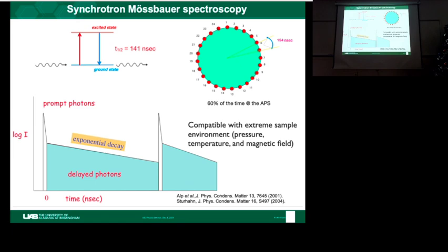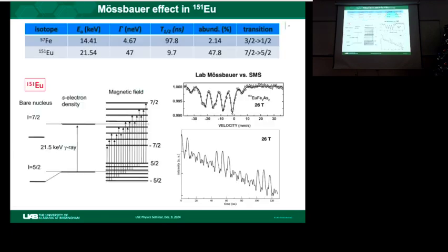And because the synchrotron beam can be focused to a very, very small size, typically several microns, or even now after the upgrade a sub-micron size, and synchrotron light has much higher brilliance than a typical lab X-ray source, you can easily integrate it with a pressure or temperature or magnetic field environment and enable you to study the materials. So here are several basic parameters for iron